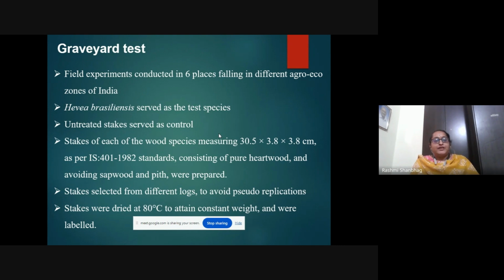The BIS clearly says that the field experiment should be conducted in 6 places falling in different agroecozones of India. For the preservative treatment, we always use Hevea brasiliensis, the rubber wood, as a test sample. The reason for using rubber wood is that it is highly susceptible to fungus as well as insects. As per the standard, we took stakes measuring 30.5 x 3.8 x 3.8 centimeters. These stakes have to be selected from different wood blocks so that pseudo replication can be avoided. We have to consider pure heartwood, avoiding any sapwood and the pith.